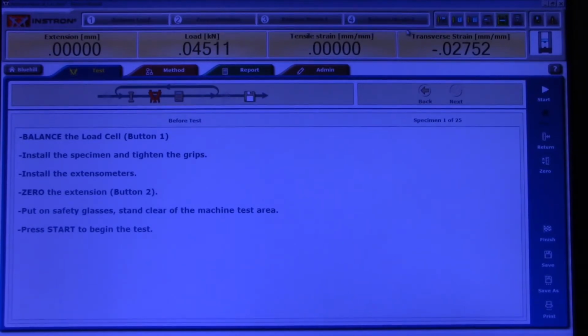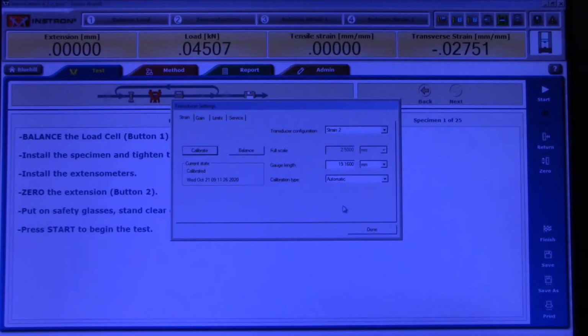My transverse extensometer, I will need to calibrate because we don't have a fixed gauge length on the transverse extensometer. Our gauge length is defined as the width of the specimen. So in this case, our width is 12.34 millimeters. And I can calibrate that.